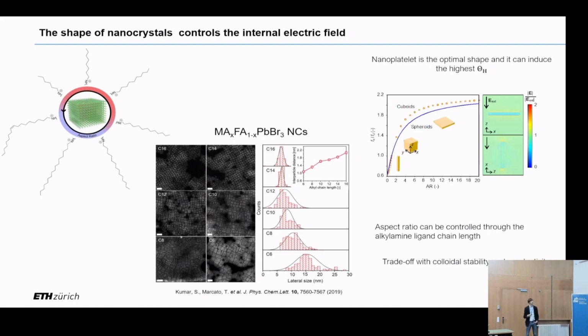And that's important because it means that even if we have a nanocrystal with an isotropic underlying electronic structure, its shape can generate an effectively anisotropic distribution, because it will effectively damp the out-of-plane dipoles, which are the ones we want to kill. And this linked very well together with the observation, still from our group, that we could achieve quite a huge degree of control over the aspect ratio of MAFA lead bromide nanocrystals by playing with the chain length of the primary alkylamine ligands. So we had a way to use this shape, even in weakly confined nanocrystals.